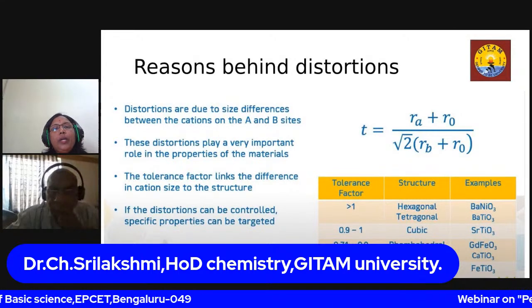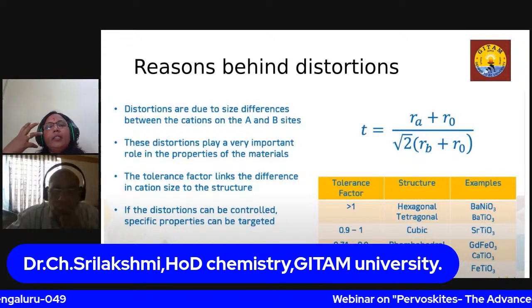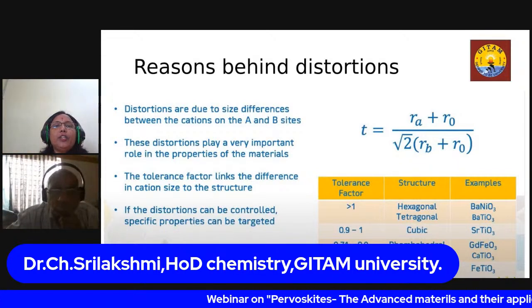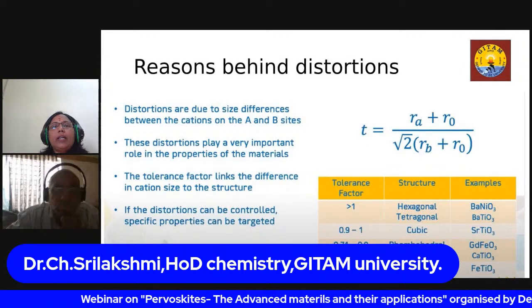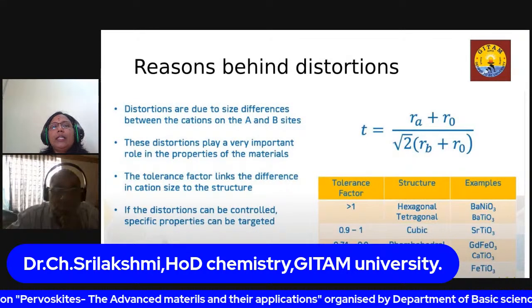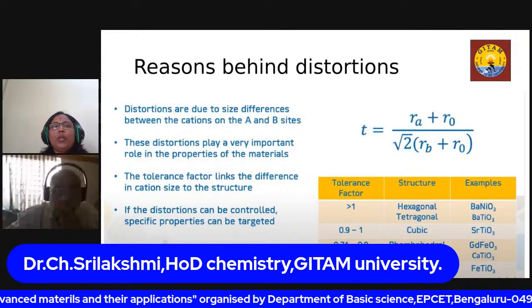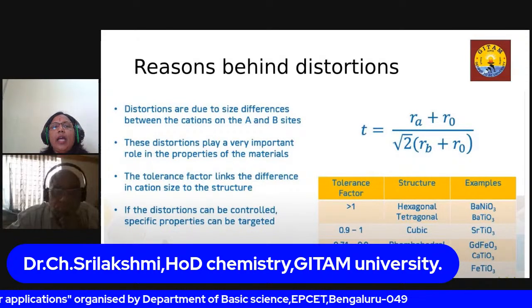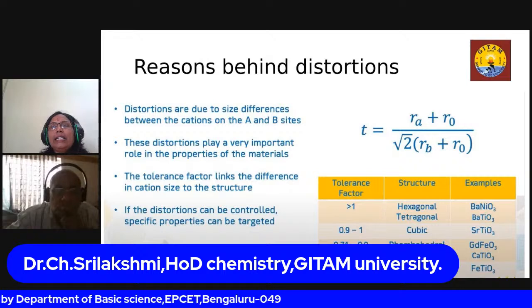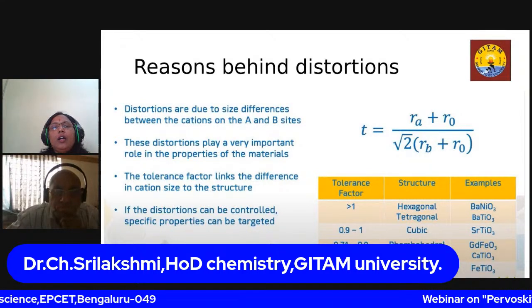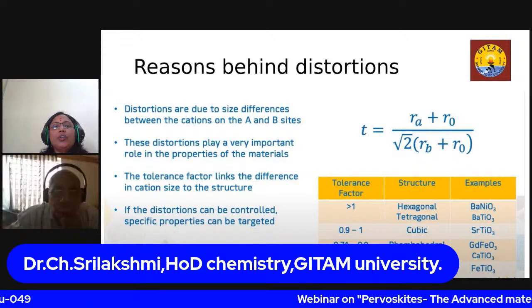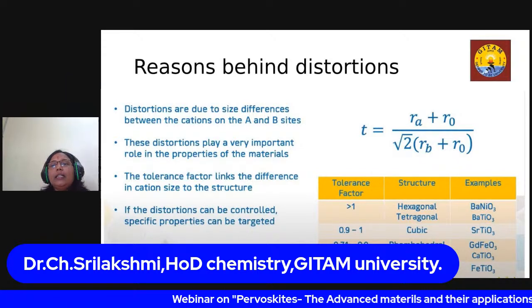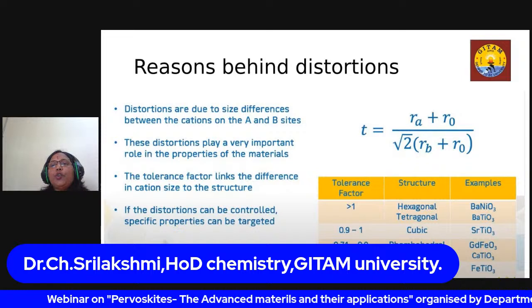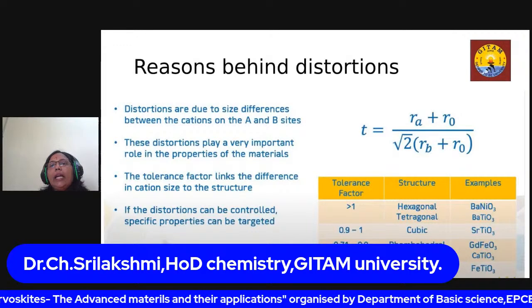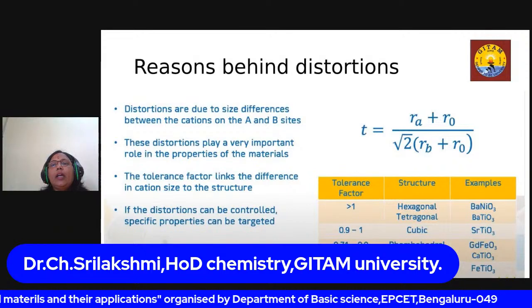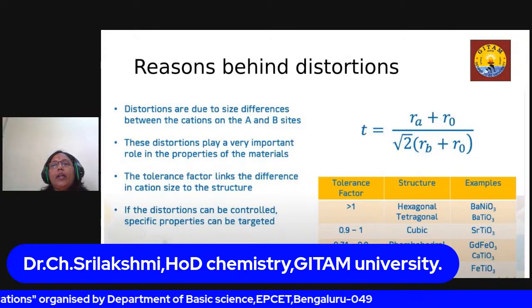That's fine. Okay, so what are the reasons behind the distortions? Distortions are mainly due to size differences between A cations and B cations. These distortions play a significant role in the properties of these materials, and the factor called the tolerance factor links the difference in cation size to the structure of the perovskites. T is equal to the ratio of the ionic radii of the A cation and oxide anion to the ionic radii of the B cation and oxide ion.